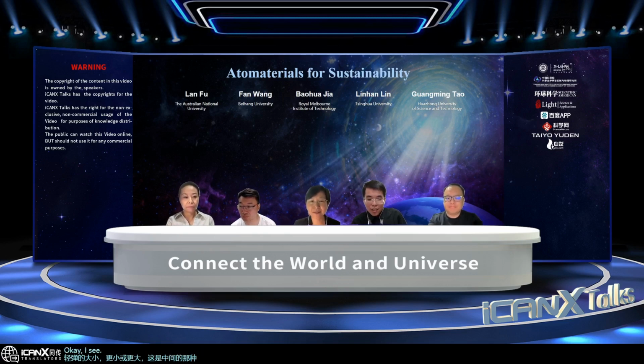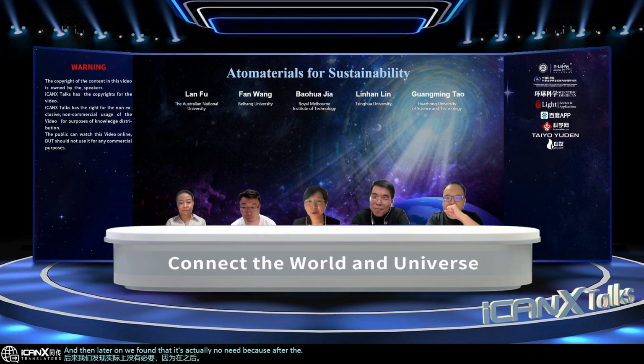Okay, I see. So we know the graphene oxide flakes are dispersed in some solvent like water, right? So do you need to introduce some repulsive force to make sure the flakes will not stick to each other? Yeah, very interesting question. Originally, we thought the same. And then later on, we found that it's actually no need, because after the synthesis, they all have negative charge. I see. They have repulsion naturally.